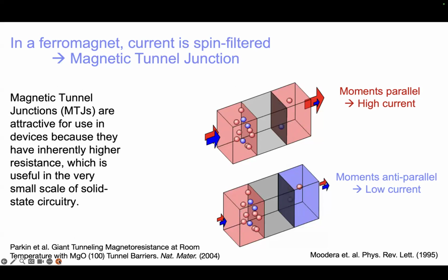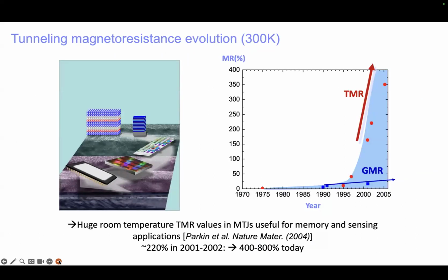But essentially, all the other concepts of engineering to make it function and be responsive to small magnetic fields are unchanged. I'm going to come back to some of those ideas later. But nevertheless, this tunnel junction enabled even further increases in the capacity of the magnetic disk drive. This is just to show you this spin valve device where the essential physics is that of giant magnetoresistance. The magnitude of the resistance change at room temperature is just a few percent, 10%, whereas the tunneling magnetoresistance has changes in resistance in one of these junctions, when the magnetization of two electrodes is switched from parallel to antiparallel, of several 100%, even at room temperature.